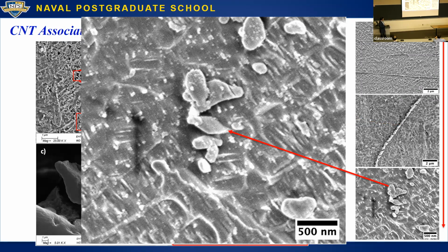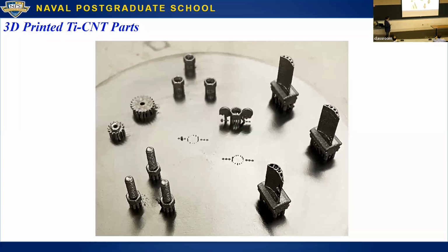These carbides will then essentially break down into the individual little platelets here that you see, in part because when you melt each layer, you're actually remelting 3 or 4 layers underneath. So you're remelting the material, causing a turbulent melt pool that can break these apart as they form. So in these composites, we have all three: single carbides, linear chains, and individual CNTs. And we're able to make these 3D printed structures, very complex shaped. These are all titanium CNT, and you can't really attain a lot of these intricate shapes with just about any other processing method.